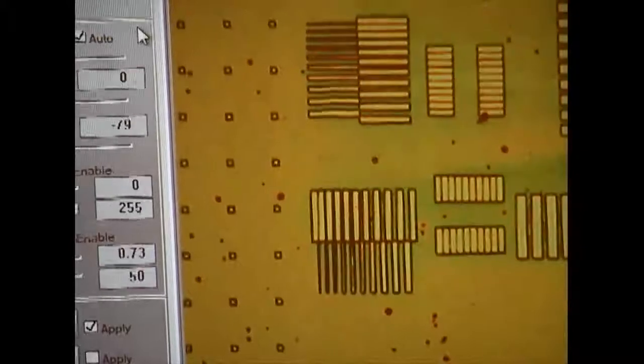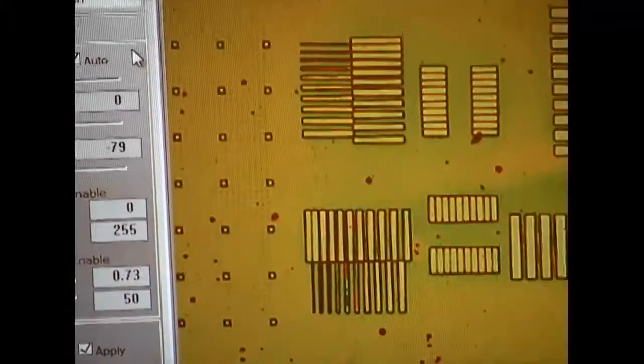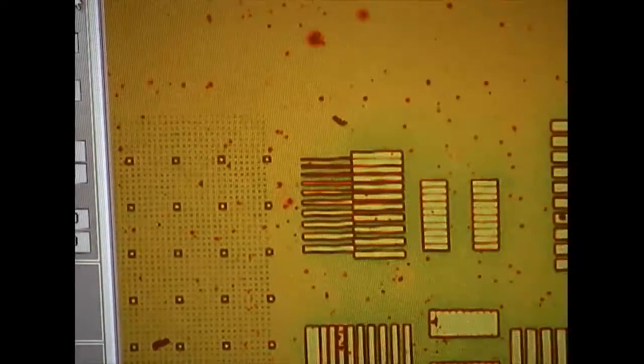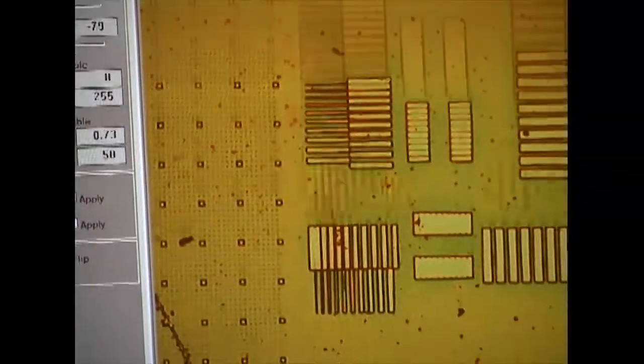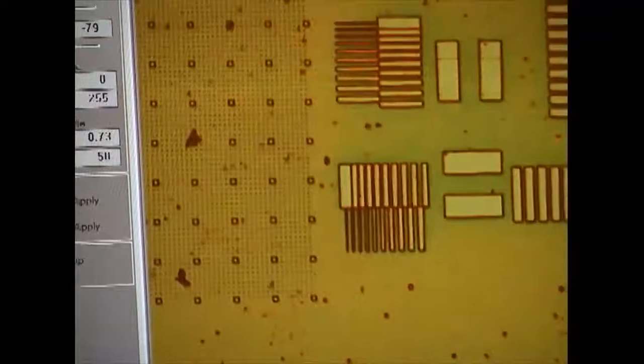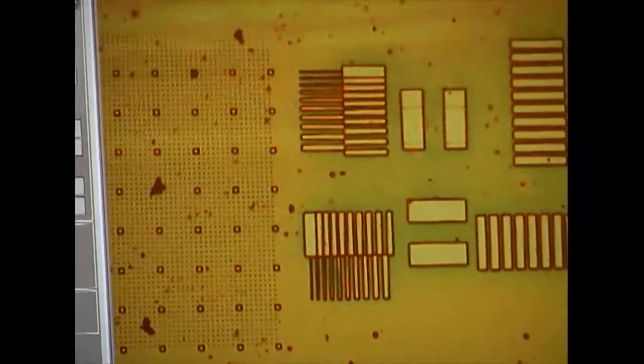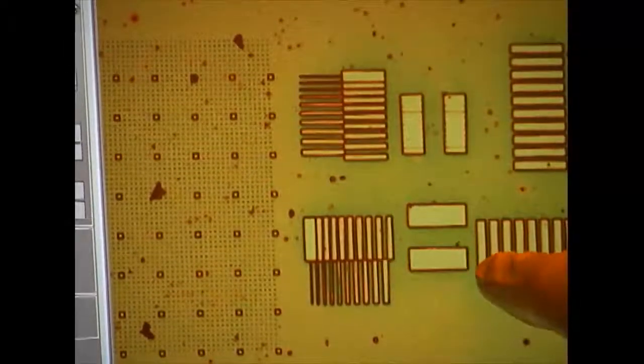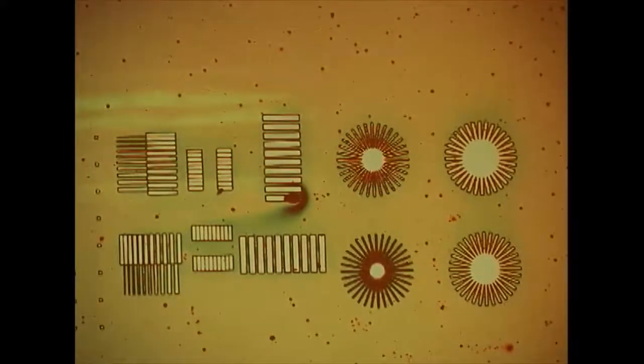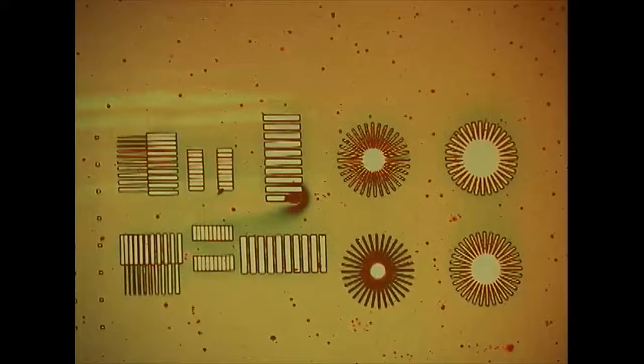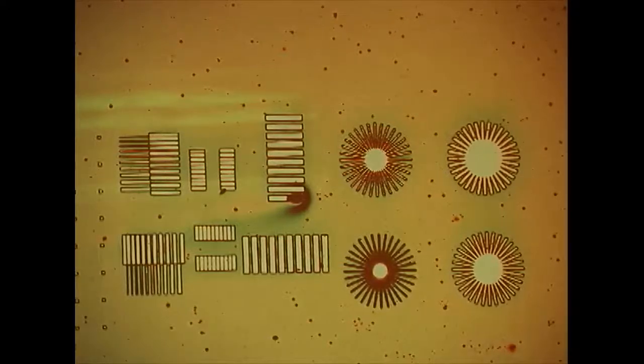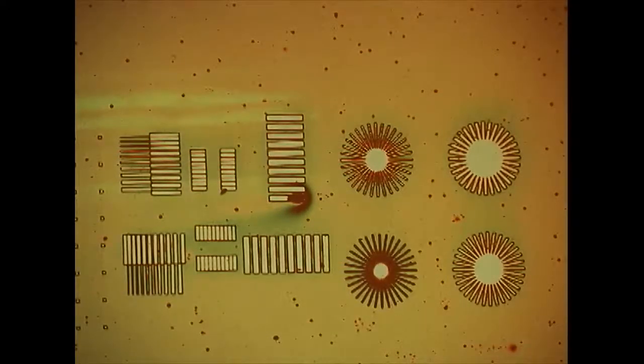As we move up in intensity, what we'll start to see is that beautiful gap starts to become narrower and narrower. You can see here that some of them are present, some of them are not. And finally, when we overexpose, we can see that these gaps simply disappear. And from this result, I happen to know that the best and most appropriate exposure is 70%.